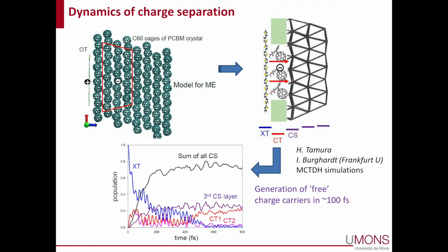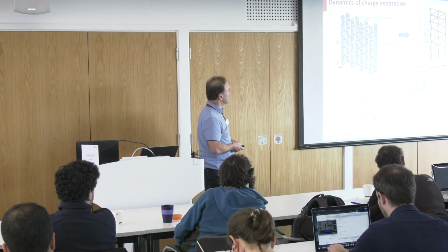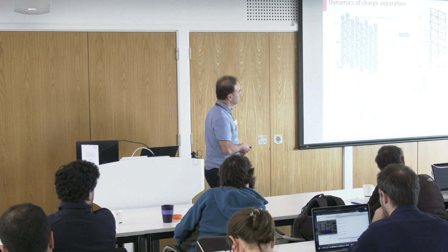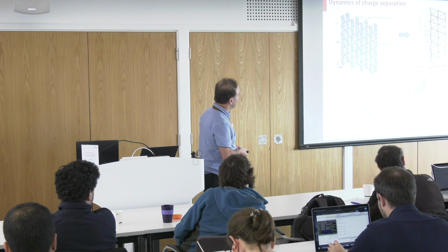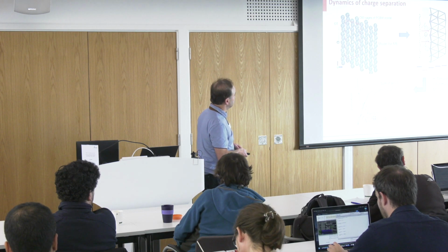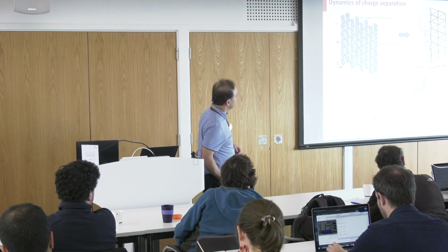And you can see from this quantum dynamics simulation that the charge generation takes place over time scales that are very fast because of this extended delocalization. So delocalization in those states is important for charge separation, clearly.